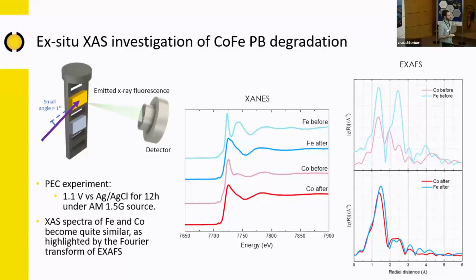Now, this was a preliminary experiment we performed on these photoanodes, in particular the Prussian blue structure, which is the one I'm going to talk about mostly from now on. And you can see here that we start from a structure. These iron spectra are just shifted on the energy scale of cobalt, just for comparison. You see that we start from a structure for our catalyst, but then we try to see what happens after a photoelectrochemical experiment that lasted 12 hours. And we see that both the iron and cobalt structures have changed quite a lot. So the XANES and EXAFS spectra are completely different after the photoelectrochemical experiment. Now, the question was, why does that happen, and when does that happen? Does it happen as soon as we put the electrode in contact with the solution? Does it happen once we apply a specific potential? Does it happen when we shine a light onto our photoanode?